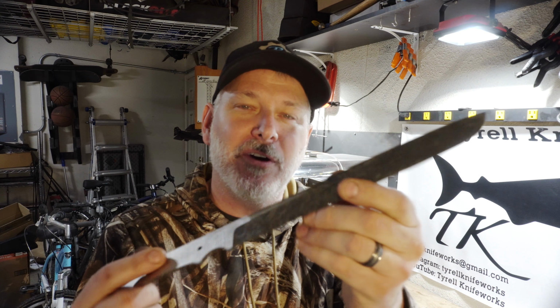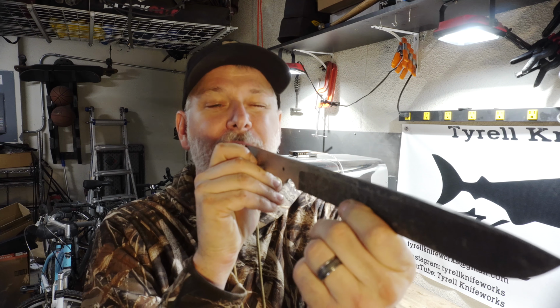The knife so far has turned out perfect. It's perfectly straight. It's exactly where I wanted as far as hardness, maybe a tad higher than I wanted at about 60.7 or something like that. You know, maybe a half point higher than I wanted, but that's totally fine. I could always temper it more if I wanted to and bring it down a little bit, but we'll see. That's the point of doing this test multiple times, to get it exactly where you want it.